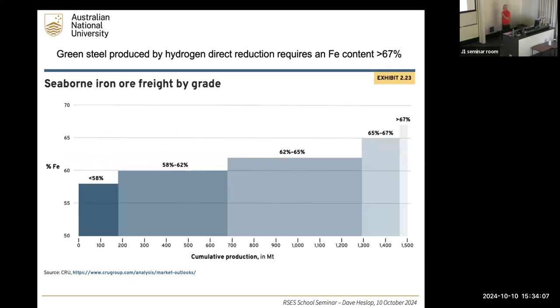For the technology as it stands at the moment, using hydrogen as the reducing agent, you're going to have to work with ore that has an iron content above 67%. And when we look at this plot of production of iron ore versus the percentage of iron, the greater than 67% that's suitable for green steel is this little bit here. What's that, maybe 5%, maybe less. Everything else is at too low a grade to actually be used for green steel production. Hence these headlines on the ABC and so on saying that Australia may be disadvantaged because of the quality of its iron ore. So this is a real problem.